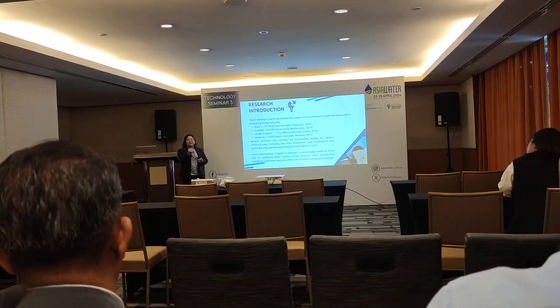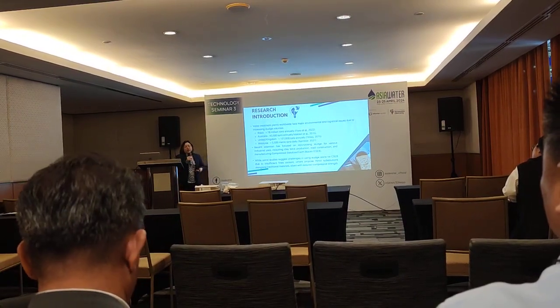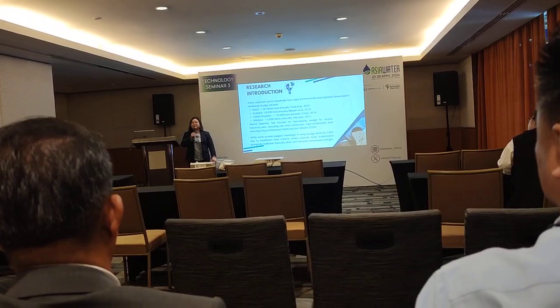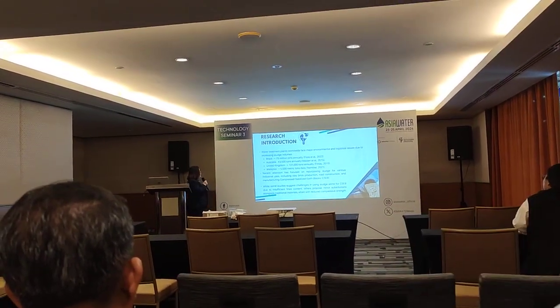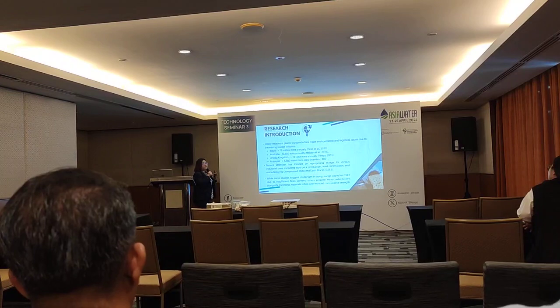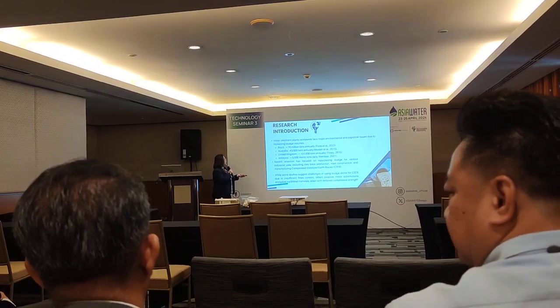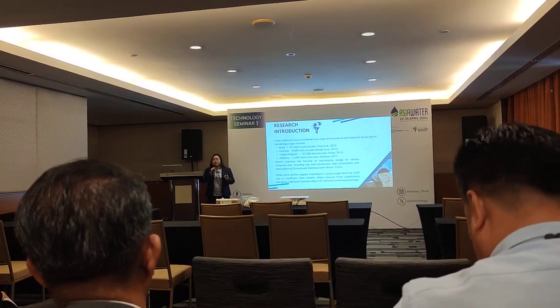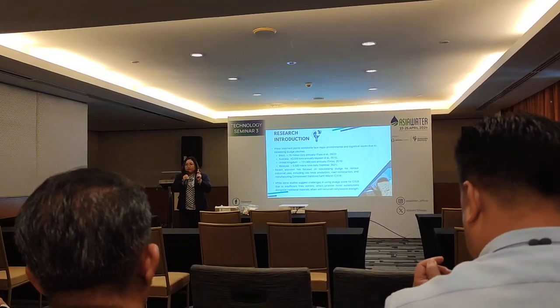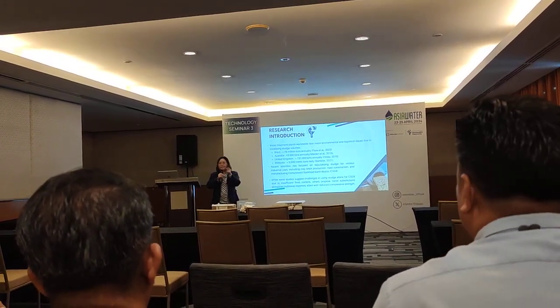Recent attention has been focusing on repurposing this sludge for various industrial uses, including clay brick production, road construction, and manufacturing of compressed stabilized earth blocks, like what we did. While some studies suggest challenges in using sludge alone for CSEB due to insufficient fine contents, others propose minor substitution alongside traditional materials, but with reduced compressive strength. In the production of brick, one of the most important parameters is to ensure that the brick produced meets the required compressive strength.